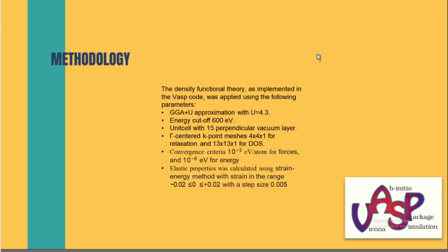So we use the density functional theory as implemented in the code. We use the GGA+U approximation with U equal to 4.3.